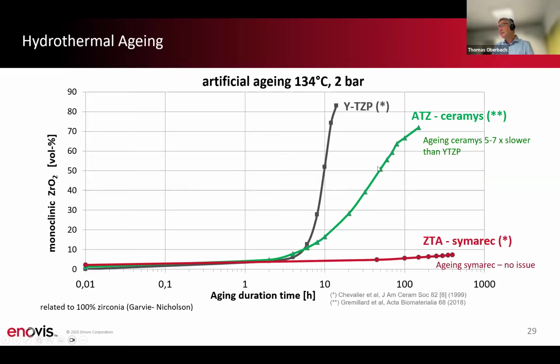And as a comparison with ATZ, we have a comparable volumetric phase content concerning Garvey-Nicholson related to 100% zirconia after 40 to 50 hours. That means, and when this corresponds also 1 hour, 1 year, then the monoclinic phase content occurs with 50% after 40 to 50 years, which is not clinically relevant. That means we see aging in the laboratory, but without relevance for the clinical case.